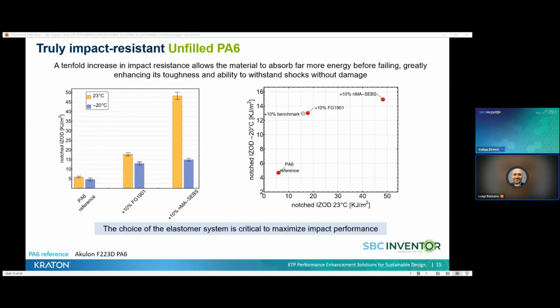Especially at room temperature, the impact enhancement is tremendous, about 10 times with respect to the reference, but also at sub-zero temperatures, it's clearly visible. The remarkable improvement in impact resistance achieved with this novel maleated SEBS shows that when it comes to impact performance, choosing the right molecular design of the elastomer is absolutely critical to maximize the results.